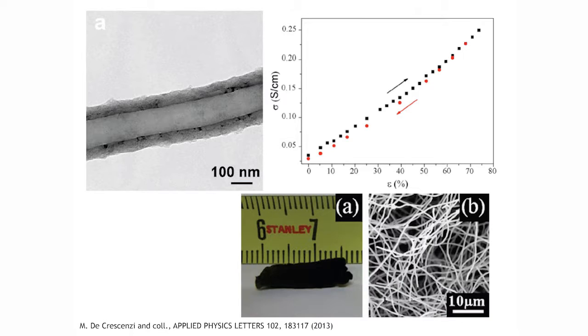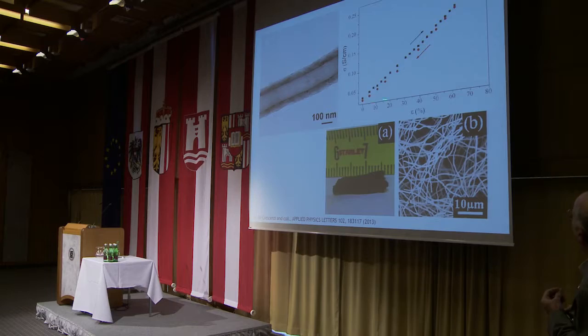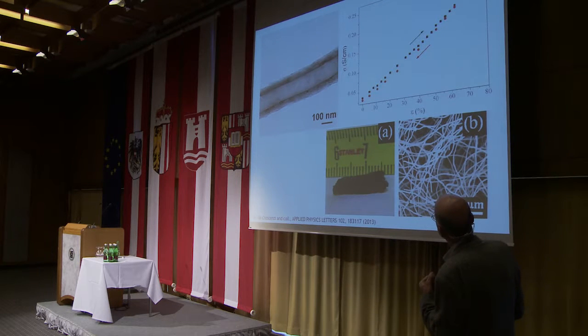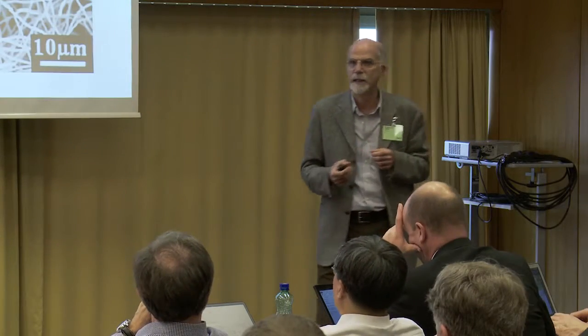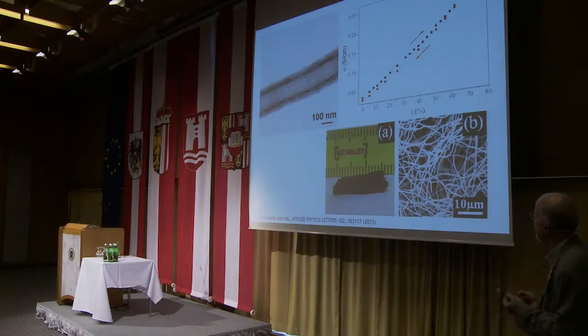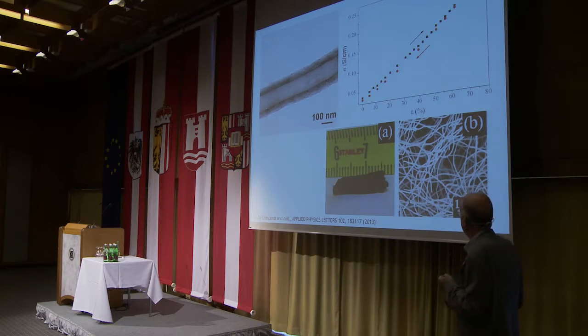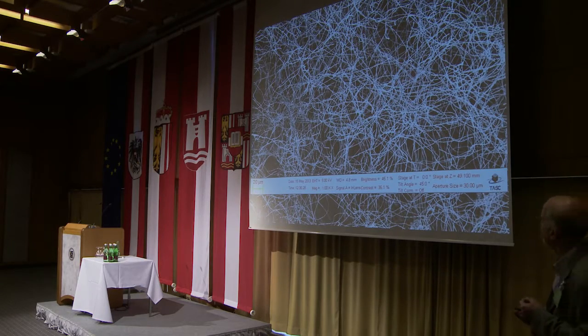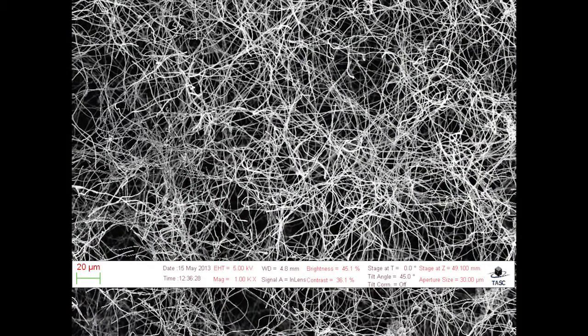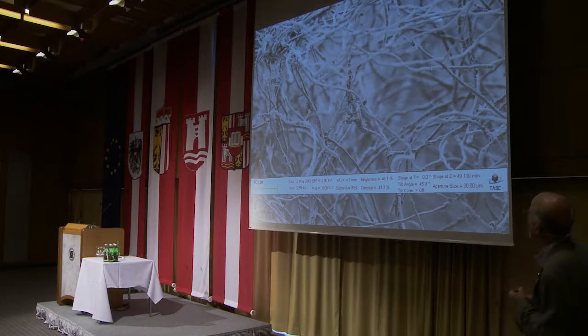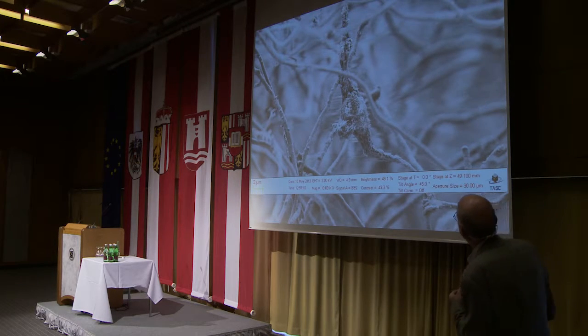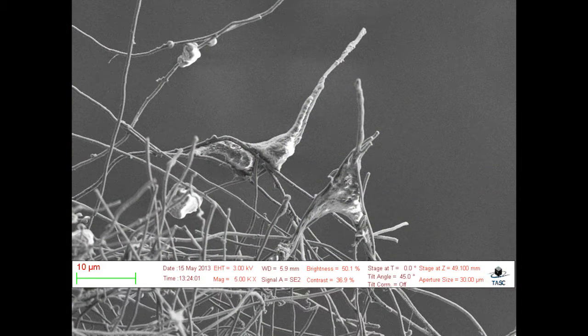So we had to change strategy, and we used these carbon nanotubes, which are produced in Roma by Maurizio De Crescenzi. They have relatively high conductivity, and they are very big carbon nanotubes, but they are especially in the form of sponge. So it's a relatively spongy, elastic material, which can be really treated like a very easy material. And so this is the shape of carbon nanotubes that we have used. You can see the three-dimensionality, and neurons grow attached to these fibers in a very, very tight contact, very similar to what we have seen before.